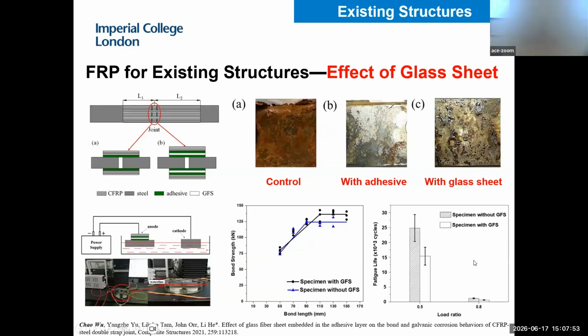Our recommendation is that for applications without any fatigue issue, it's okay to use glass fabric to avoid galvanic corrosion. But for fatigue applications, it's better not to use glass fabric. Instead, you have to carefully treat the bonding surface before bonding carbon fiber, because all you need is to avoid contact between carbon fiber and steel. If you already have a layer of glue, the glue, if done properly, can separate the two materials.